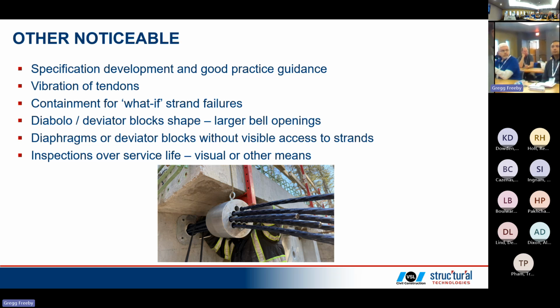With the tight fit of the bundle inside the duct, did you have any issues with elongations, and did you do an in-place friction test? We did an in-place friction test. We did our elongations, and they came out good, within the expected theoretical ranges that were calculated. Yeah, it was okay, even with such a tight situation.